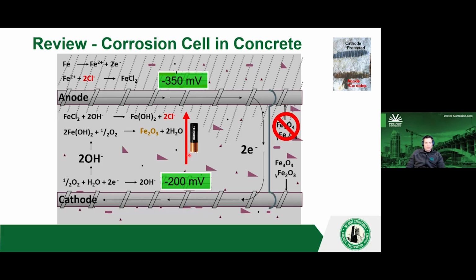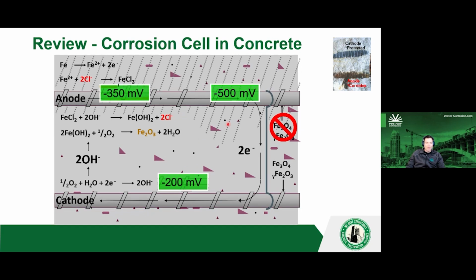Now, you don't necessarily need this second bar in this completely passive area to cause corrosion. You can have areas on the same bar that just have a higher chloride exposure. So in this case, you can see this area has a higher chloride exposure than the one adjacent to it. While both are showing signs that they're in an area that is more than probably actively corroding, only the most negative or hazardous area is the one that actually corrodes. It's going to be the most electronegative.